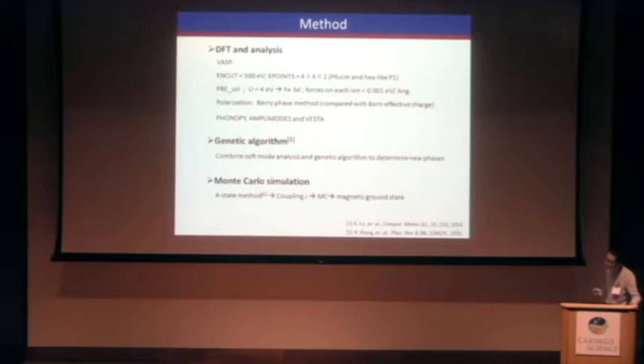So we are using those methods. First, the DFT calculations, which I will just skip, and the genetic algorithm combined with soft mode analysis to predict new phases. And for the magnetic structure, we use DFT to generate exchange parameters and then put them into Monte Carlo and see the ground state.